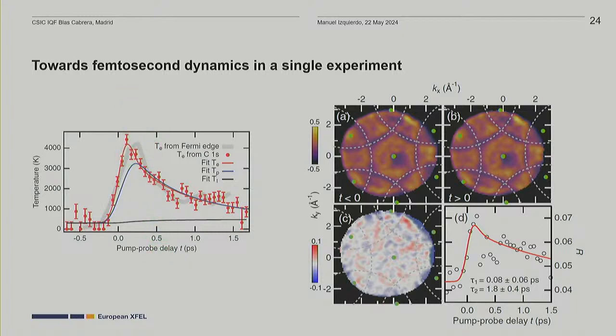They did a simultaneous experiment of photoelectron diffraction, and they saw that in spite of the high electronic temperatures, there is still a lattice, so the lattice of the system still remains, with not very big changes.